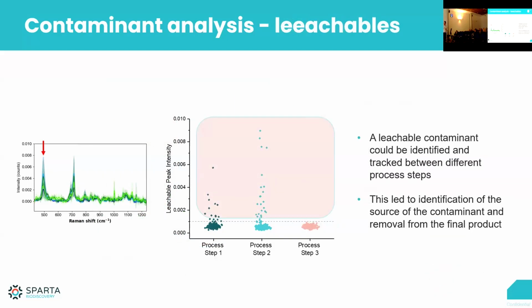This is a really big problem in other kinds of production as well, especially at larger scale. There are also larger scale purification technologies, which usually use a lot of flow-based techniques. What has recently become clear as a problem is that there can be leachables from all this tubing coming into your particles, which is contrary, because it's a purification technique, so you're trying to remove things. Of course, it's removing, for instance, excess protein in the solution, but it can introduce contaminants as well. The nice thing is we were able to detect this with SPARTA. We didn't know beforehand that there would be contaminants.